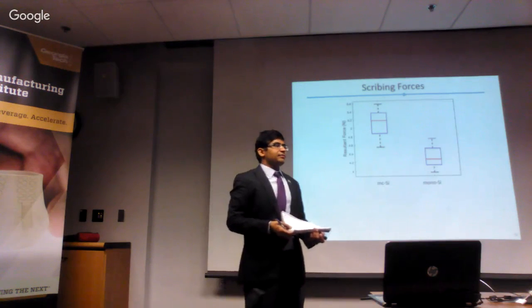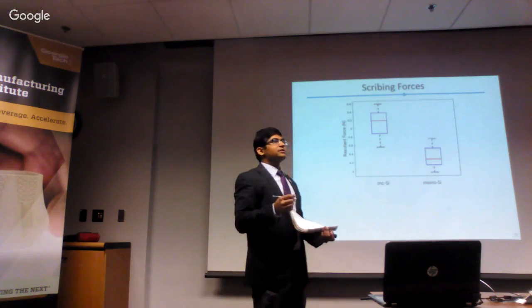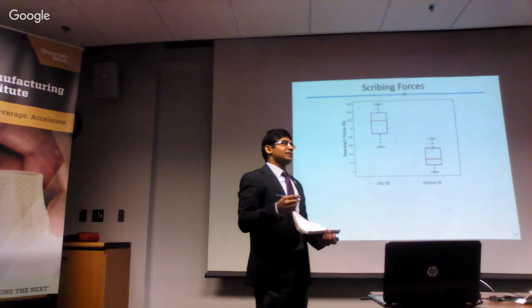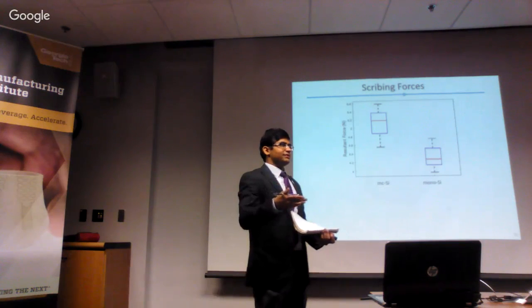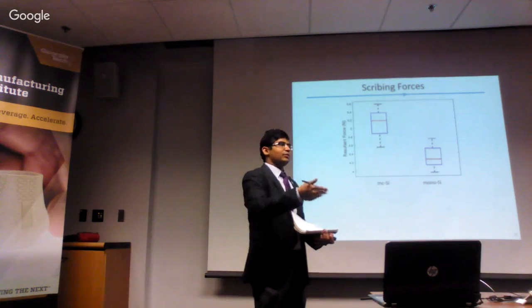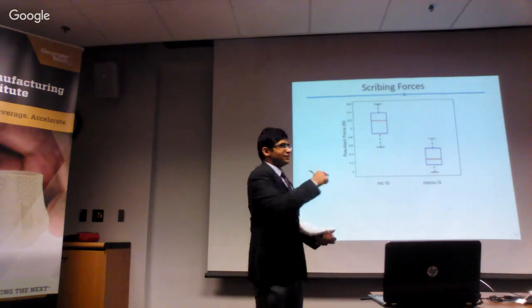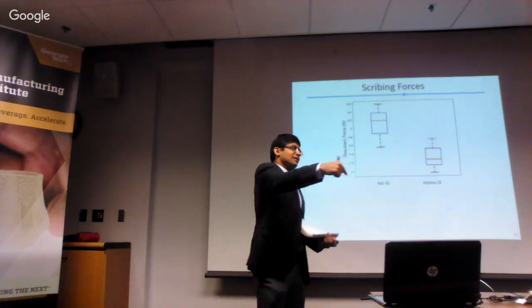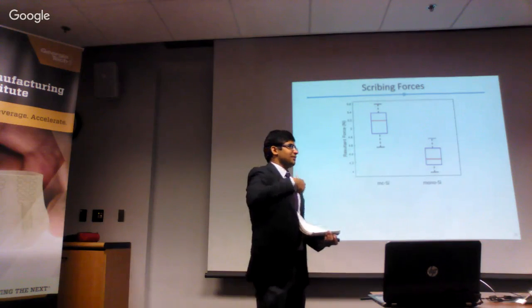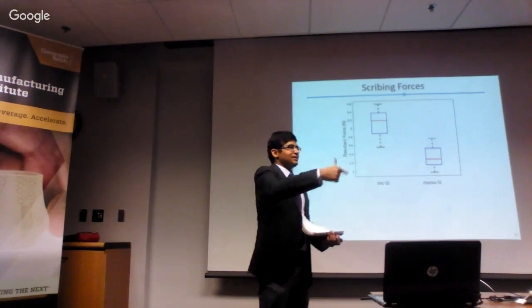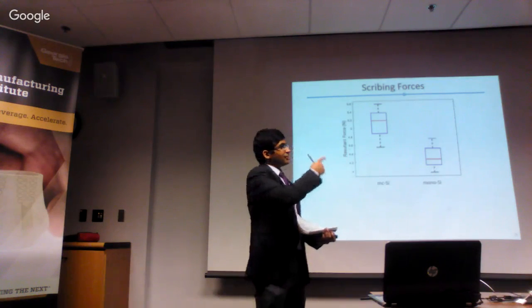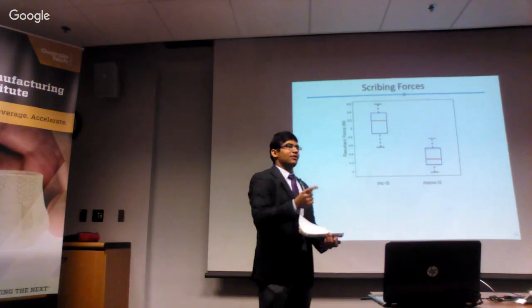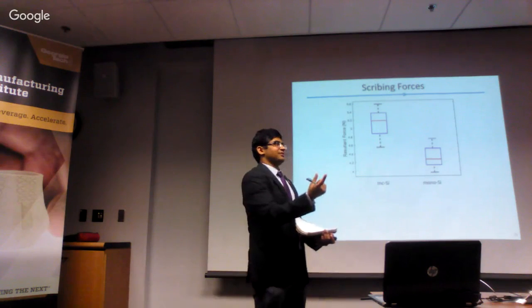And if the fracture is brittle, those oscillations are confounded with any change in K1C. Also, these forces are over 20 millimeters, and in 20 millimeters I'm encountering many grain and twin boundaries, compared to the grain and twin boundary result you saw, which was over like 20 microns.